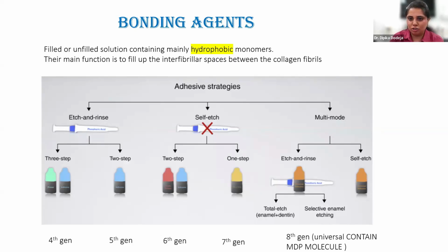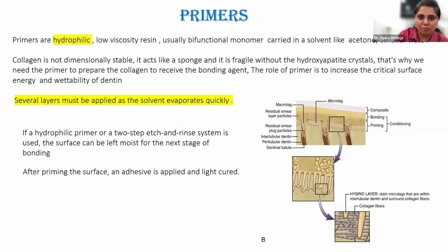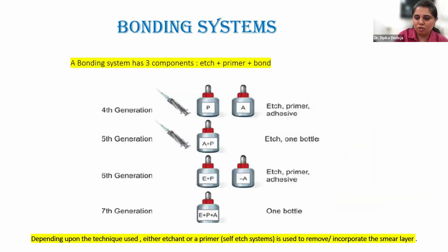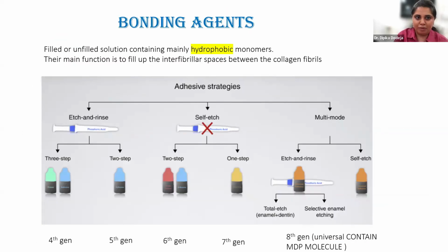tooth. So the fourth generation of bonding agents, as you can see in this image, is the gold standard for bonding because it achieves the maximum bond strength to the dentine, as the primer effectively wets the dentine, and the adhesive acts as a separate hydrophobic layer to bond to the cement or the tooth. But this is very technique sensitive, relying more on the operator's skill, because if you over dry the dentine, the collagen fibers may collapse and there will be less bond strength. Also, if you don't dry the dentine effectively, there will still be a compromise on the bond strength. So this is very technique sensitive but a gold standard.